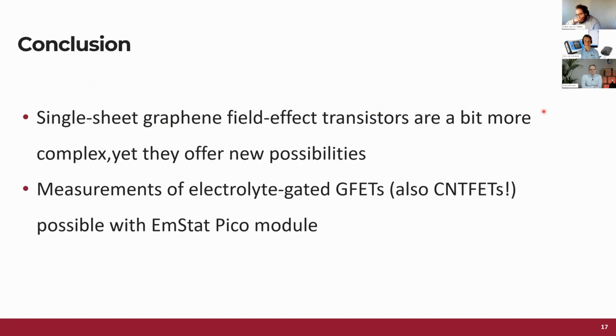So to sum up this part, the single sheet graphene field effect transistors are very nice and are a little bit more complex, yet they offer new possibilities. I didn't mention that in here, but for example, since the graphene is directly exposed to the liquid, there can be some Faradaic processes happening at the surface of graphene itself. So this is where we cross the border with electrochemistry, like classical electrochemistry, where the Faradaic processes from redox reactions are taking place. The measurements of the electrolyte gated FETs, GFETs here are possible, again, with some limited voltages, plus minus 1.5 volts, but it also allows, in principle, for measuring the carbon nanotube network FETs. This was not shown in here, but I've been doing that in my previous work as well.